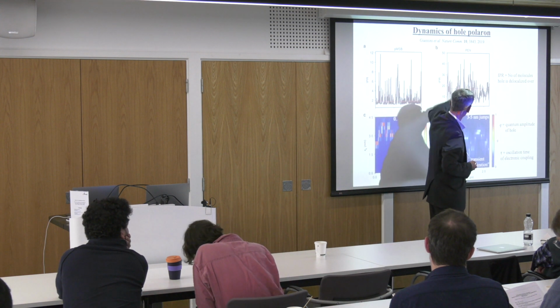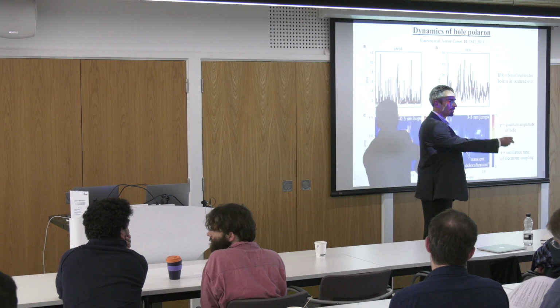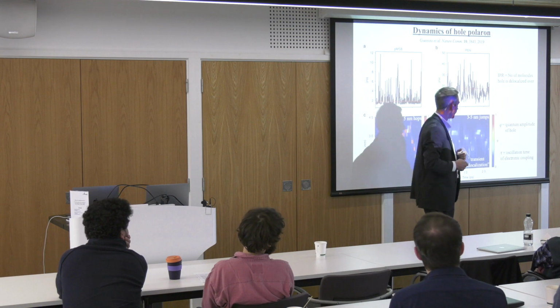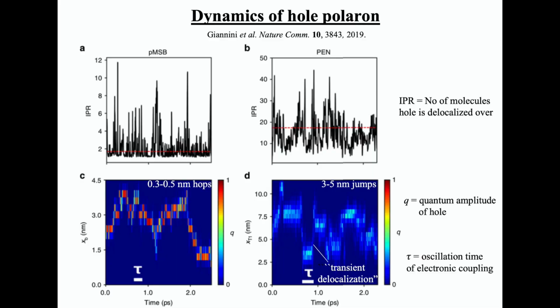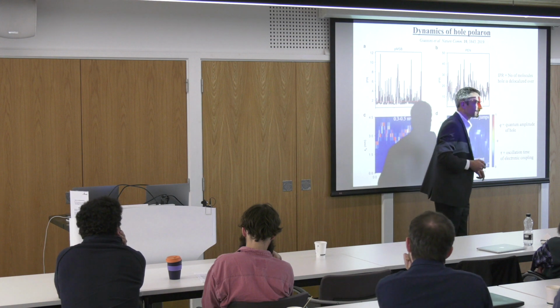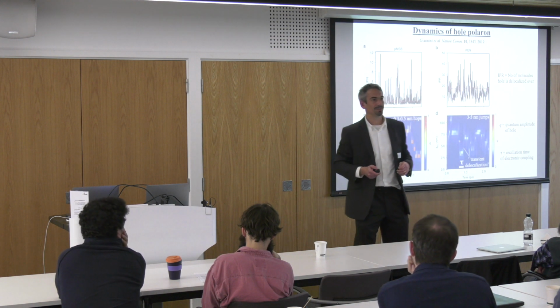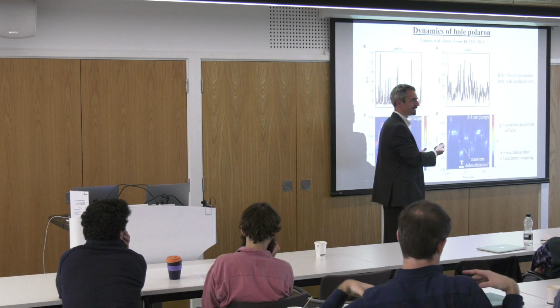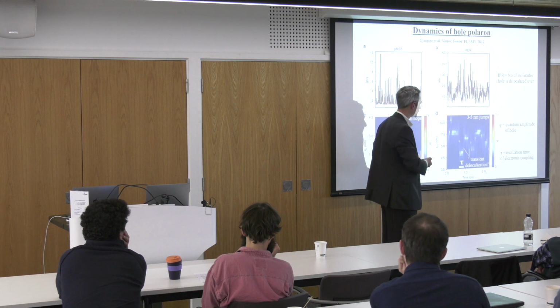So some of these things are successful. Then you have the jump. Some of the things are not successful, and then the polaron basically expands, but then shrinks back to where it originally was. And what is also very interesting is the time scale on which these jumps are happening. So the IPR of around 18 is stable on that time scale, which is roughly 200-300 femtoseconds. This is basically what the people using transient localization theory call the tau. Okay, here it's nice because we get the values for the tau directly from simulation.